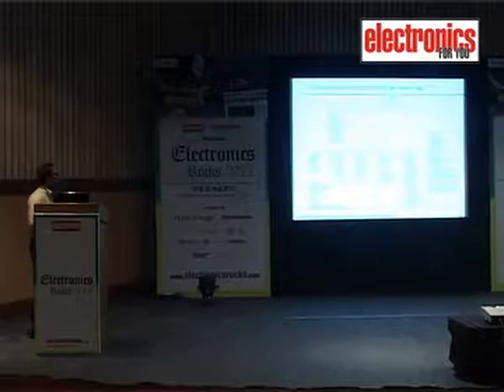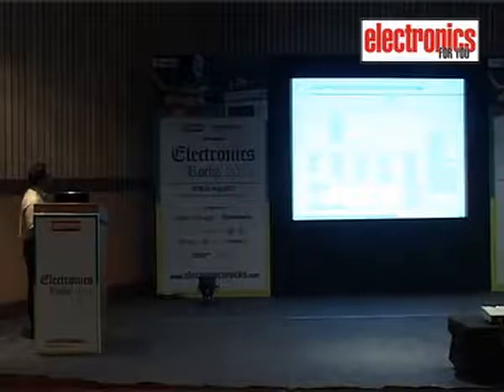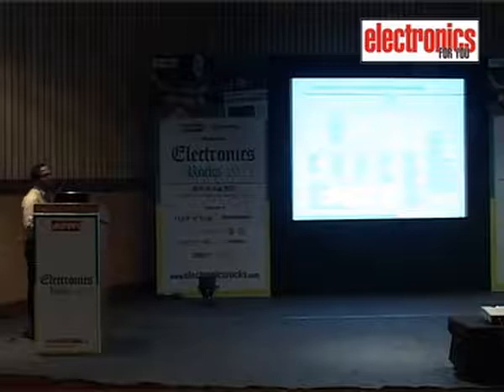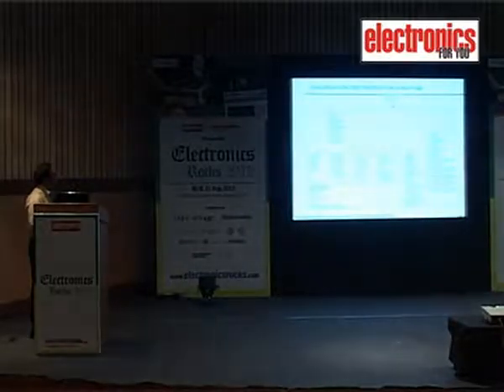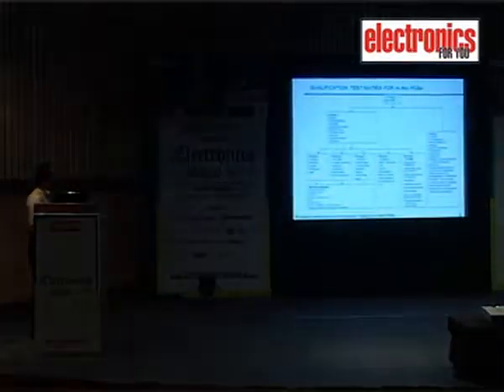Similarly, in group 3, we do current carrying capacity. That is, with a proper derating, we fix the current carrying capacities for each trace design, because that is one of the critical things: the trace or the copper track should not fail during operation. And we also subject it to long-term damp heat monitoring, to simulate humidity conditions so that the PCB does not get affected. Similarly, in the group 4 test, we do hot storage and cold storage tests. In the hot storage test, we subject the PCB to 85 degrees centigrade and keep it for 14 days. And similarly, at cold storage, we keep it for 24 hours at minus 40 degrees centigrade.